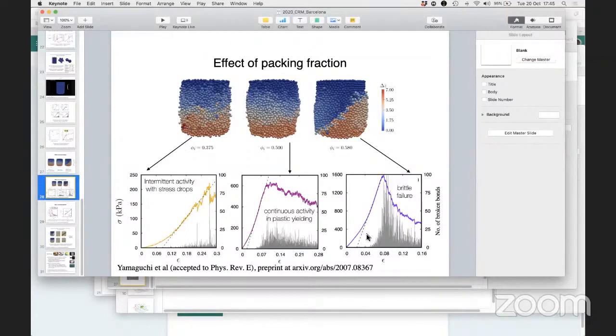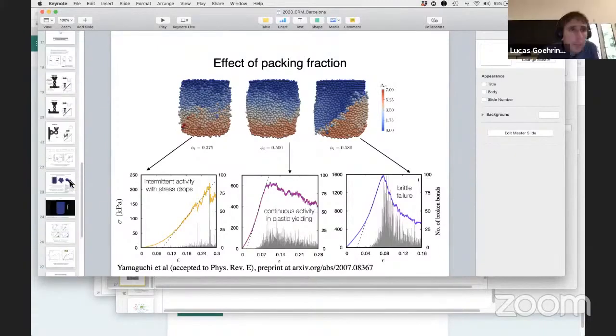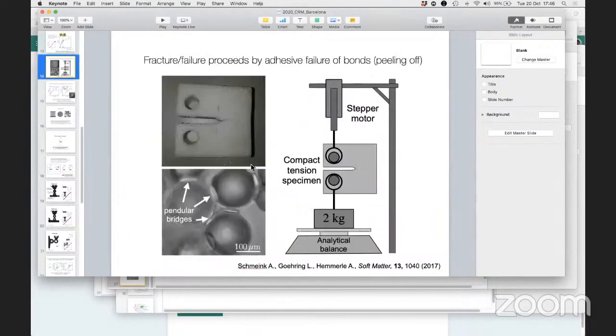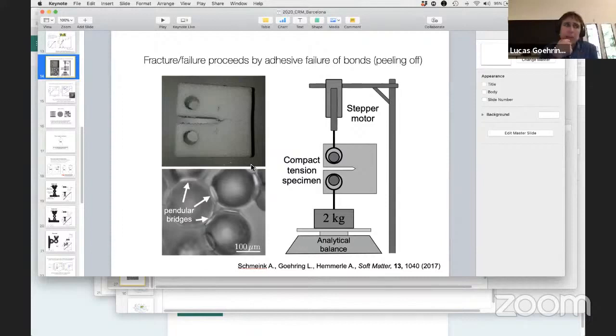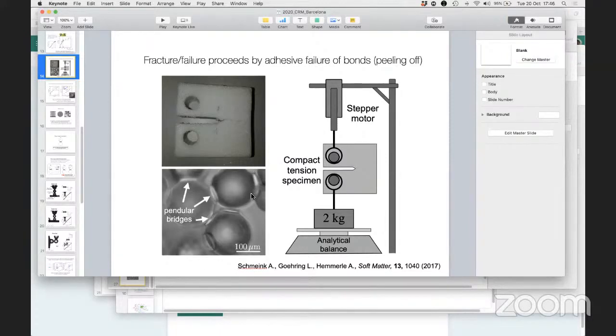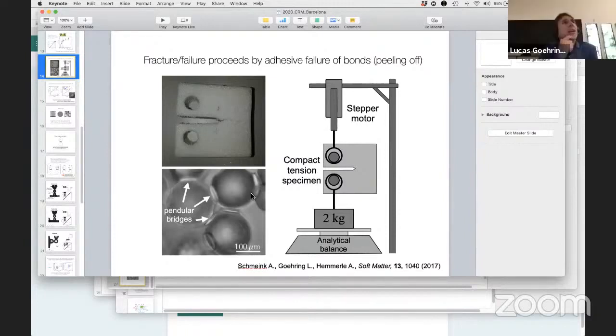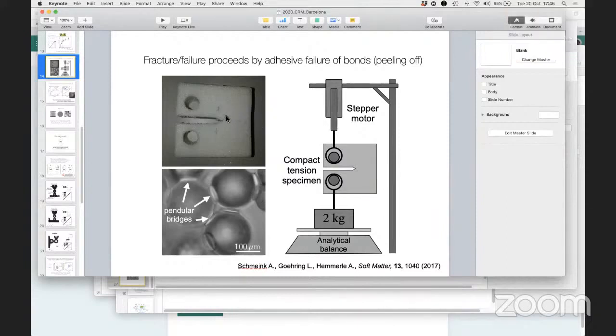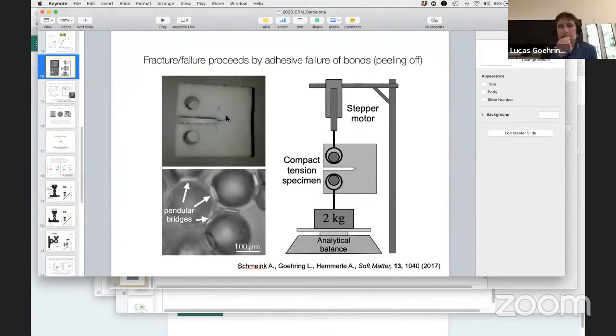And a related question about the fracture experiment that you did, the mode 1 fracture. I assume the concentration of this polymer glue should impact the failure mode. If you have a low concentration, you should perhaps see shearing bands, no? In the geometry we used, it's a notch geometry, designed to test fracture propagation. If the material is soft, then you should see a shear band, not really a fracture. In this geometry you can get something going off at a weird kink angle. Exactly. We never really saw that. I think you are right that there are some materials that will do that, but we didn't really see that.